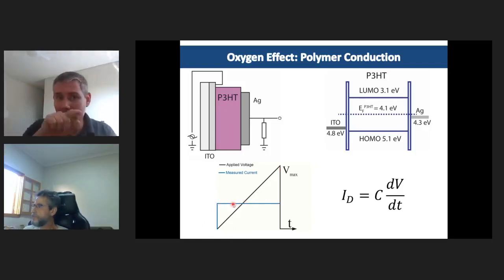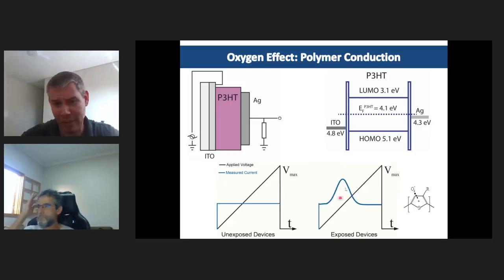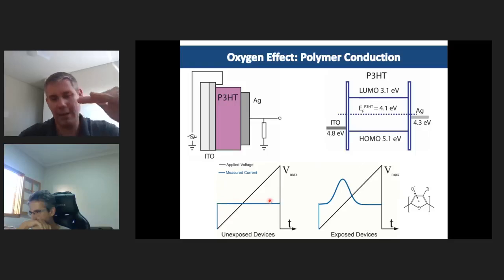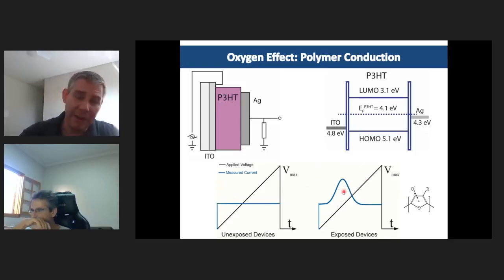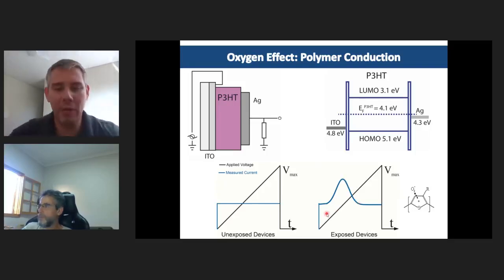And therefore, if you have any free electrons or holes within your dielectric, these are not displacement current, they are really conduction currents, and that conduction current will appear on top of this constant displacement current in this technique. This is more or less what I illustrate here. So if I don't have any charge in the semiconductor, the technique would give me only this constant current, which is the displacement current. But if I do have charges in the semiconductor, it appears as an extraction on top of this curve. So I can separate both currents.